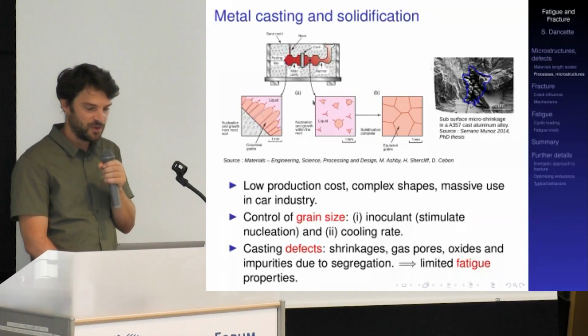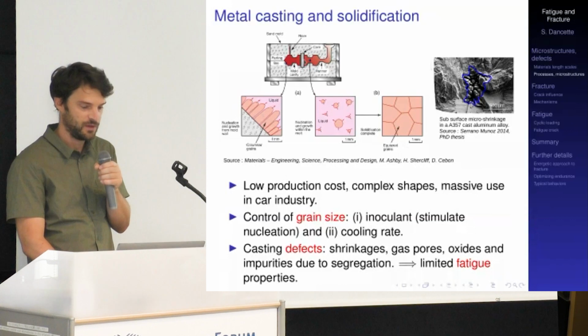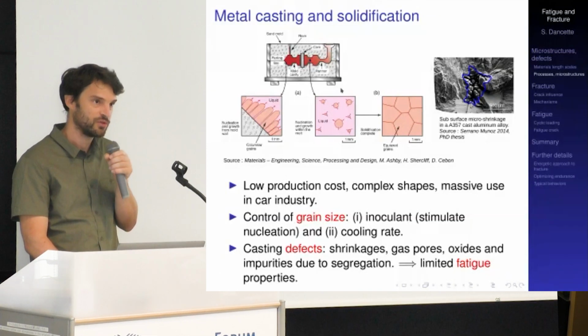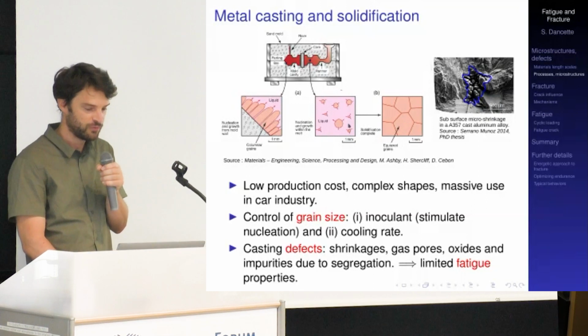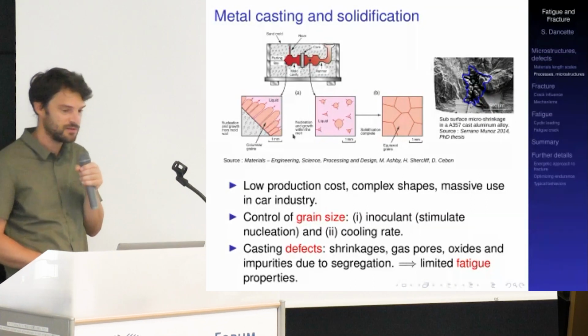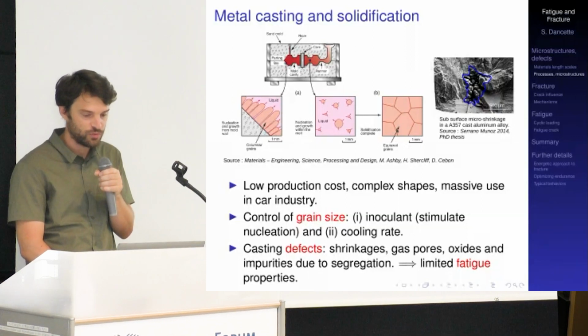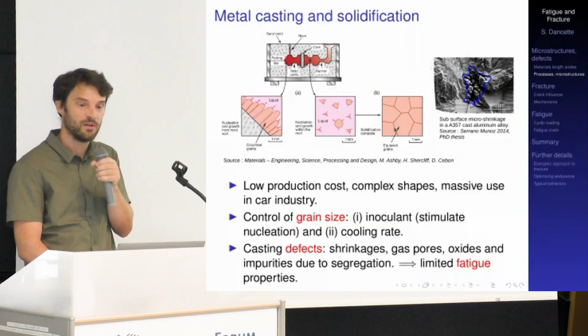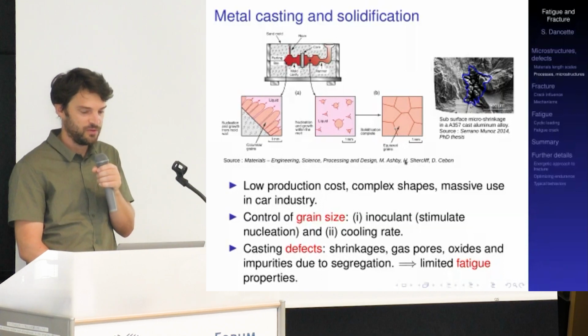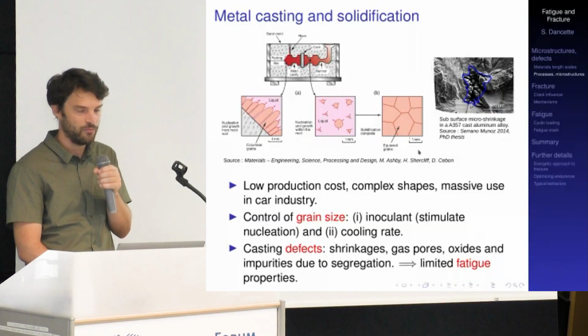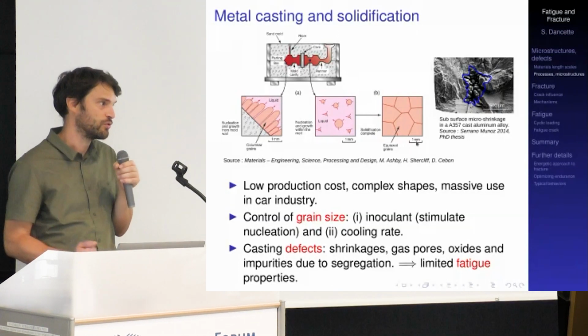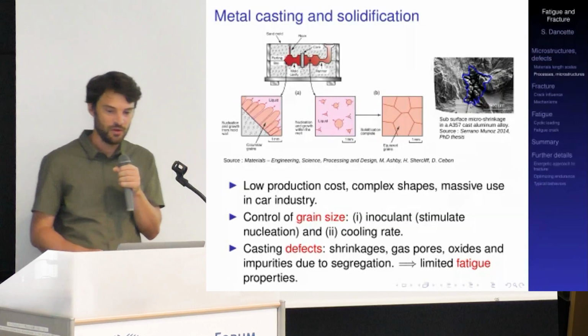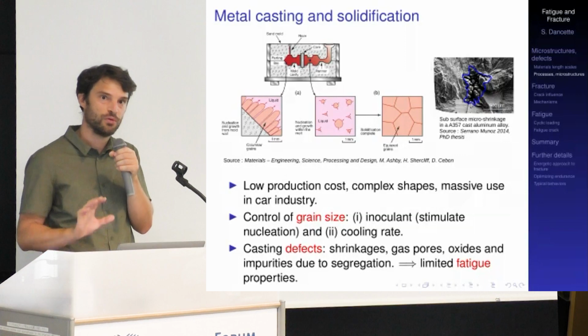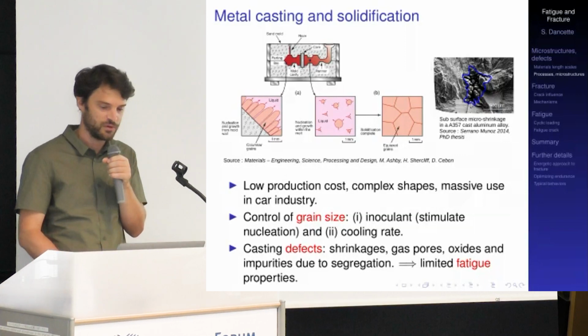And compared to this, if solidification occurs in the liquid, in the bulk, let's say, of the liquid, then you will have another type of initiation for nucleation and growth of the crystals within the melt. And then you will end up with a different microstructure, so most likely equiaxed grains. So again, you see here the scales in such solidification structure. The scale of the grains is usually in the order of millimeters compared to the usual scale of the grains in fine grained materials, engineering materials, which was, as we introduced before, rather in the order of a few tenths of microns, for example.